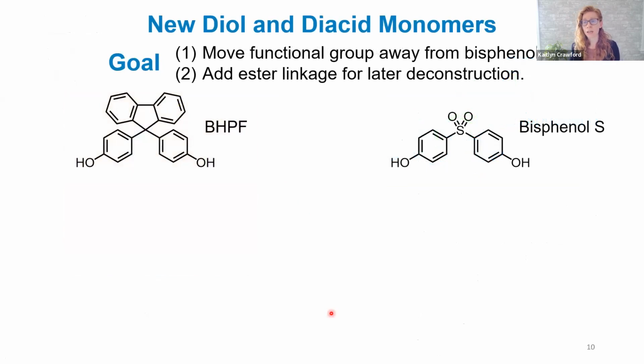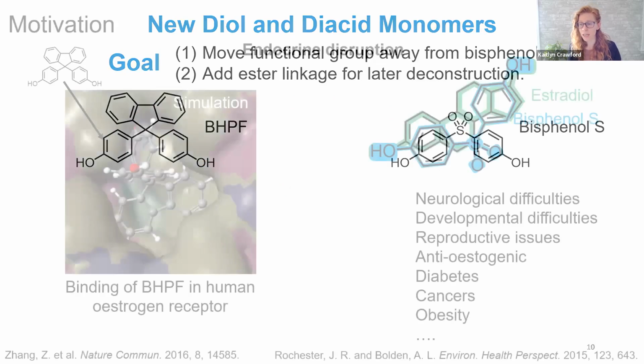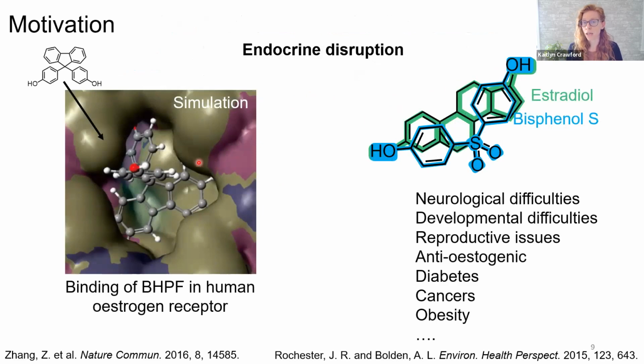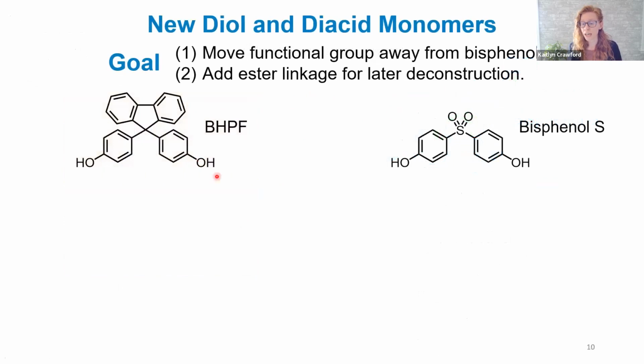And so our group decided we would tackle this in two different ways. One, there's a sustainability issue of once we're done with the polymer materials, how do we deconstruct them for later recycling or to be resorbed into the environment, assuming they would be non-toxic. And the other is that if we could potentially use these same properties of this large bulky group, and these sulfone groups are part of what give the high temperature stability and good optical transparency, but if we could move the hydroxyl groups away from this aromatic ring, then we might be able to prevent them fitting into this receptor location and they won't cause endocrine disruption any longer. So that's our hypothesis. The short version of that is we're still in the preliminary stages of identifying if our modified monomers are endocrine disruptors or not. But I wanted to share with you at least the preliminary data that we have today.